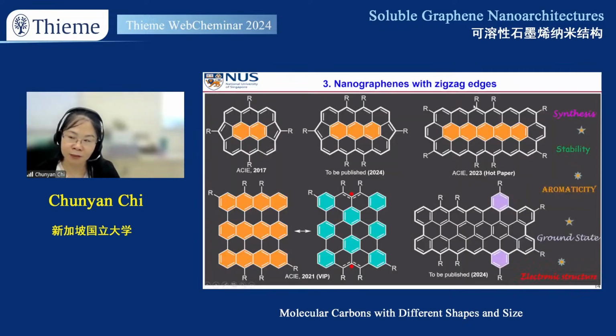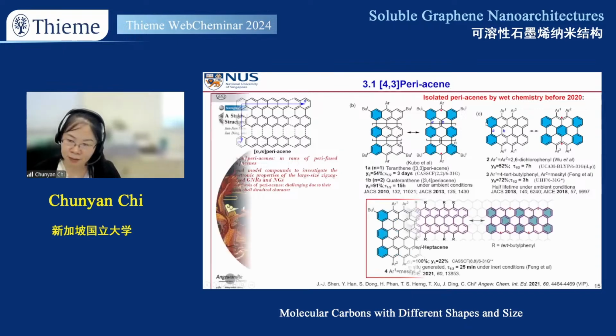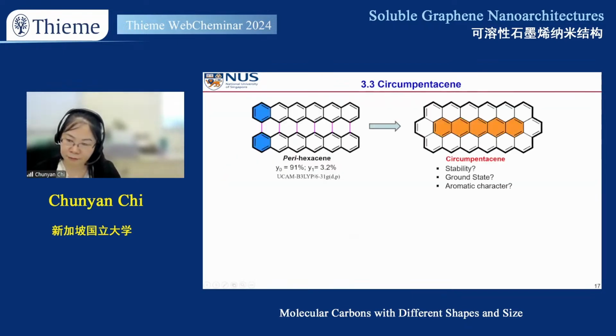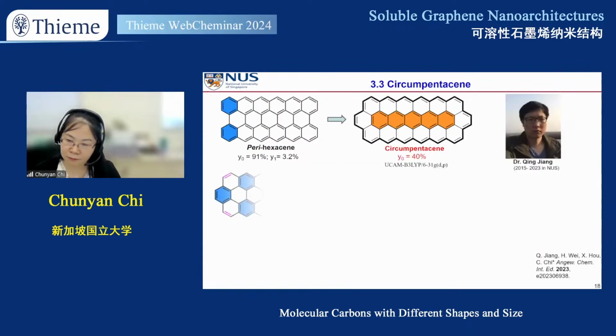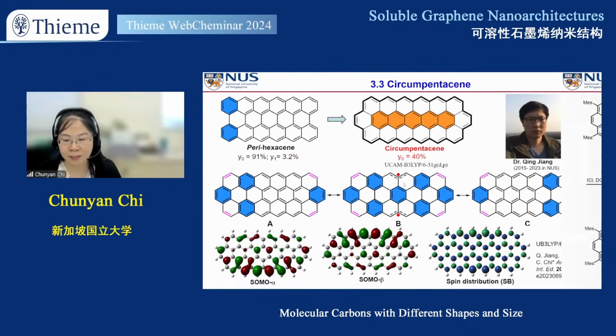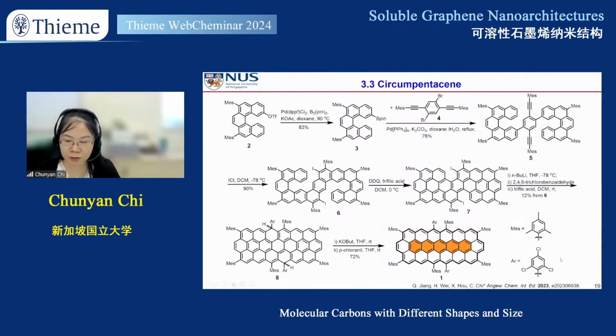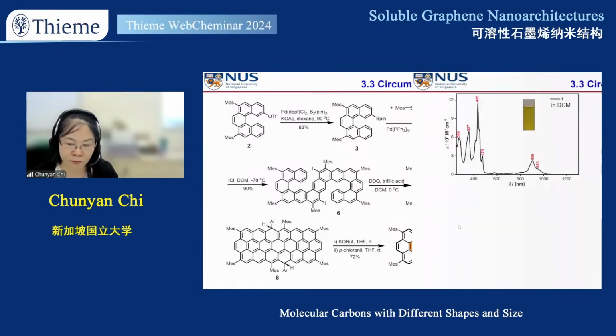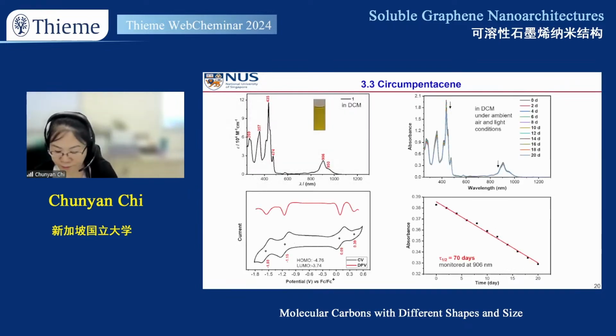So for example, in this molecule, one R group... Here, because I didn't mention, okay, maybe go to the next slide. Okay, so you see, the mesityl group is an electron-donating group, and the Ar is trichlorophenyl, an electron-withdrawing group. When we design this molecule by this strategy, as you see, this molecule is very stable. The half-life is around 70 days.